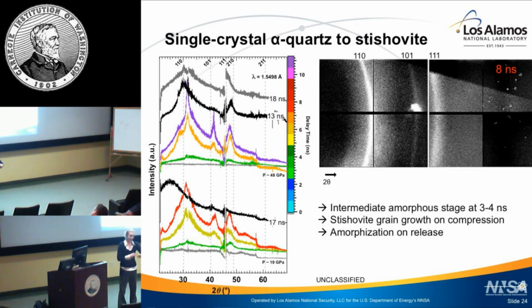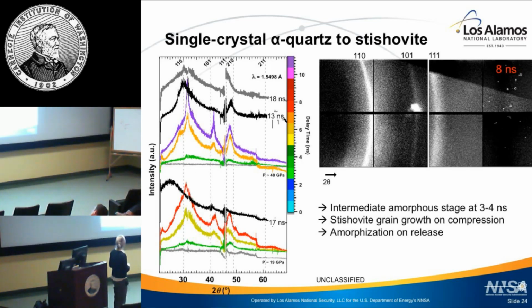But now as a function, again, of the shock wave moving through my sample, and I probe at certain time delays, so that's the colored traces here, we see quite a few features develop. So first of all, we do see crystalline stishovite. We see peaks that form that can be indexed, once again, as stishovite. But we also see some superpositioning of broad features at the same time, at maybe earlier time delays, so maybe seeing an intermediate amorphization stage going from the quartz to the stishovite, maybe, right? Then on shock release, again, for a lower pressure, say 20 GPa, we see a diffuse signal come back. But again, at the higher pressure, so this is almost 50 GPa, we see the crystalline material hang on a little bit longer, as well as the superpositioning of the stishovite.